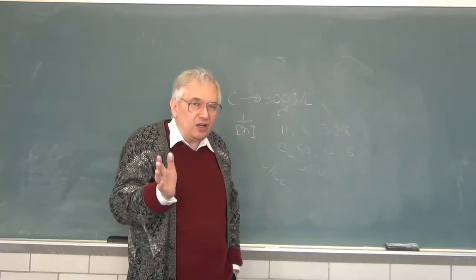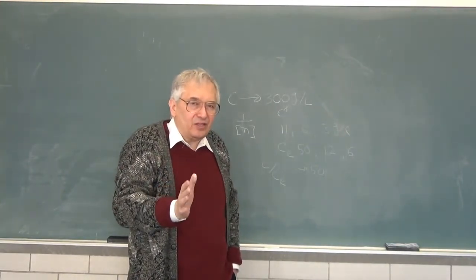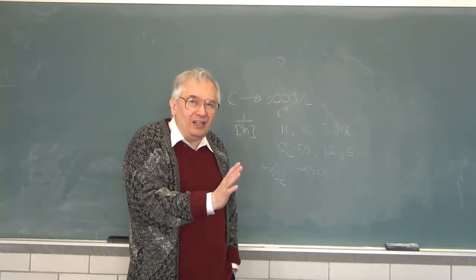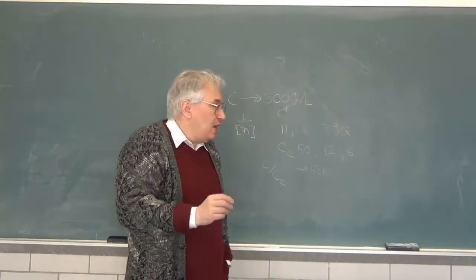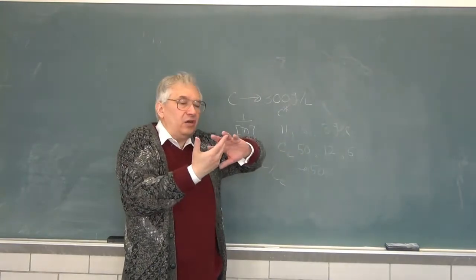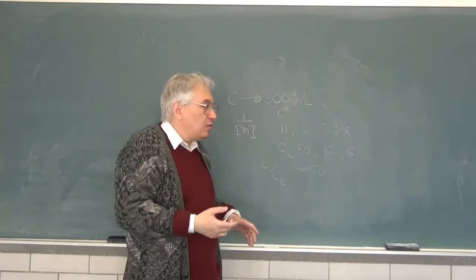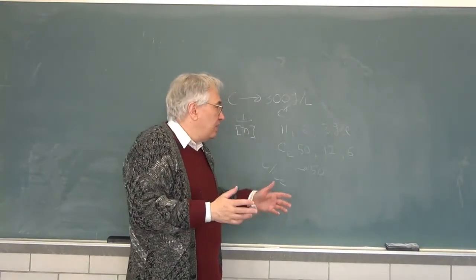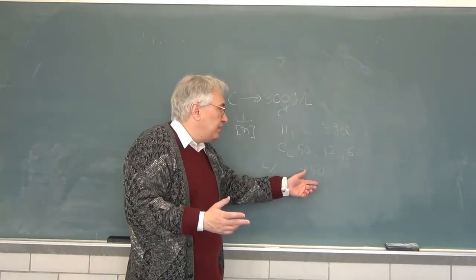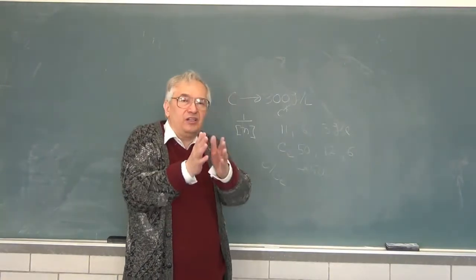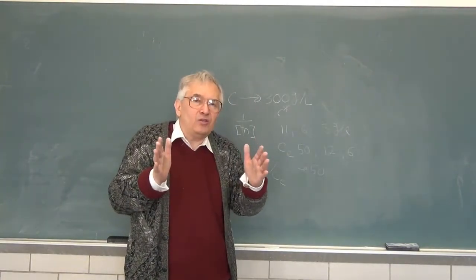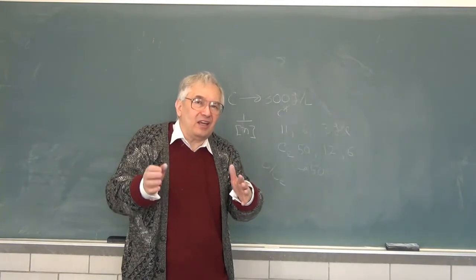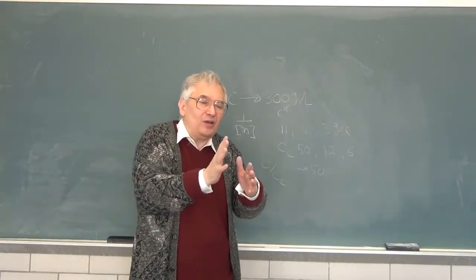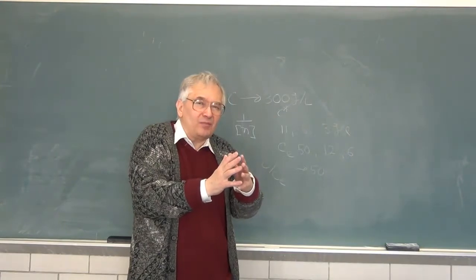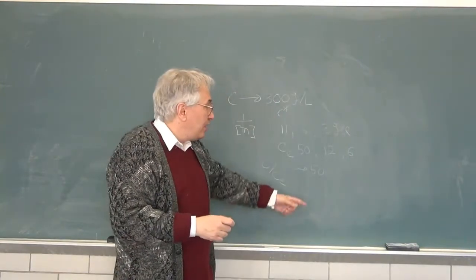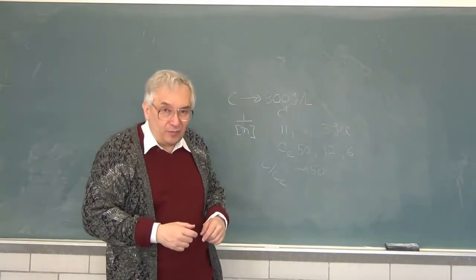Now, the transitions we are talking about here are not thermodynamic phase transitions. It's not that you chug up to some concentration, you have hit the solubility limit, and now you have a solid phase appearing right at that point. Instead, you have chains that are intertwining with each other, and at some point, in terms of this de Gennes model, the intertwinings become rheologically effective. And they become rheologically effective over a range which most versions of the theory do not calculate. That is, it starts becoming effective. You run up the concentration some imprecise amount, and now it's really effective. But they got up to quite high concentrations.